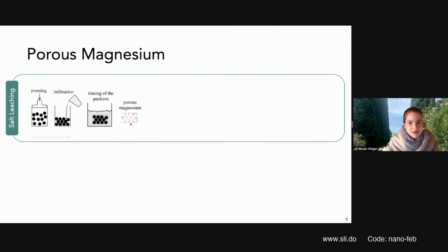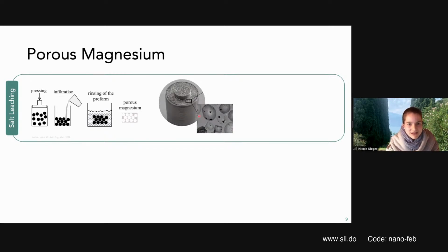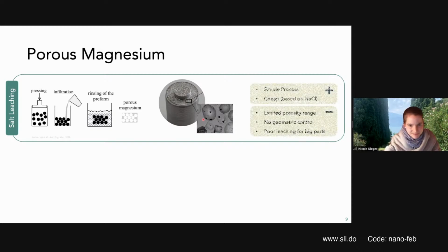So if we look at the real samples, that's how they look like. So we have these really nice uniform pores. However, we cannot really control the shape and the size of them. And also, as you see, they're connected through tiny little spots. So for thick parts, it's really hard to get out all the salt from the implant.